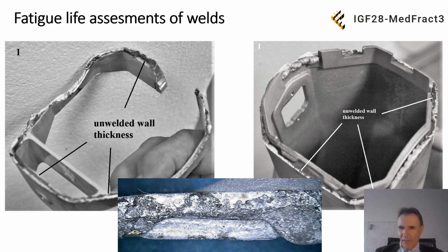Here is the problem with weld joints. This is the second problem in these technologies. A weld joint is a very complicated part for fatigue life assessment. A few approaches exist for how it's possible to do it, and they are also included in standards. Another problem is that the weld process on bicycle frames is more complicated due to the non-constant thickness of the wall in these tubes.